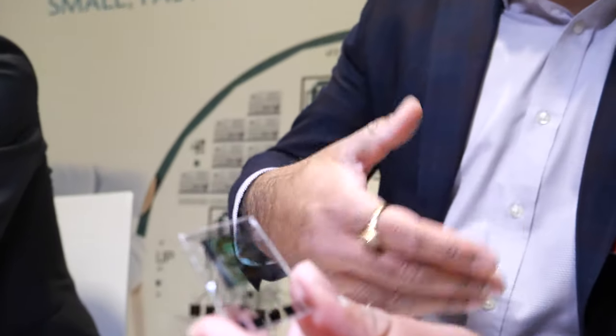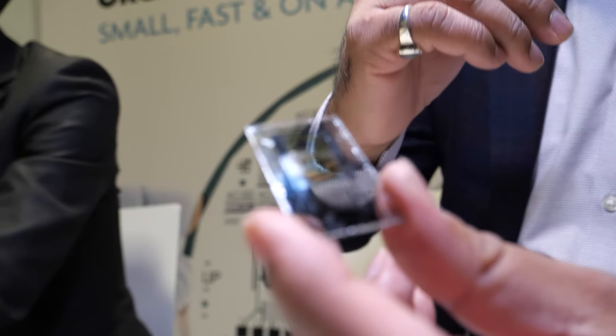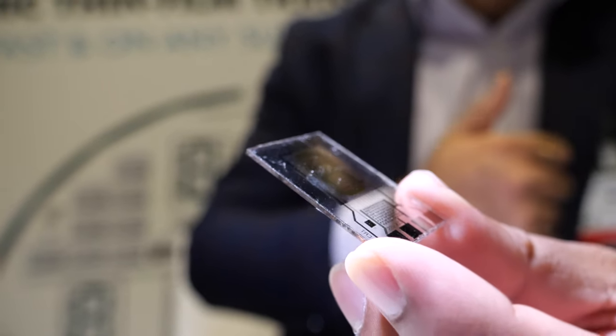This is the collaboration between IMEC and Fujifilm. The other innovation is on the topology of the TFT itself. This is an organic TFT where the contacts are at the top. We have also replaced gold contacts with copper contacts as a work in progress. The purpose is to make production of these TFTs compatible with flat panel display fabs, because they prefer top contact and don't use gold. Most legacy organic TFTs are bottom contact and use gold.